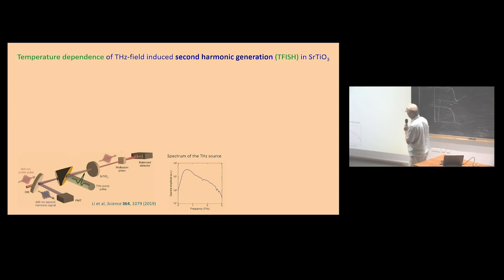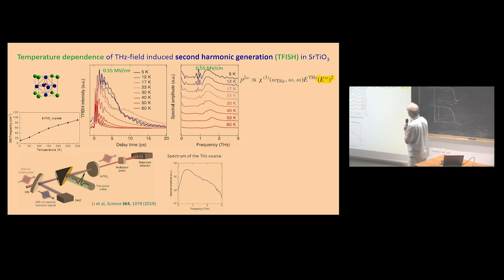In the same issue of Science another paper was published from the group of Nelson, and they again investigated strontium titanate, but they pumped it with a single pulse with the peak around 0.7 terahertz. They pumped the strontium titanate and probed it at 800 nanometers, and they measured second harmonic generation. And again, they observed a strong increase of second harmonic generation intensity. If you calculate the Fourier transform, you see one single peak, which corresponds to double the soft mode phonon frequency, which softens on cooling. And then it splits at low temperatures, probably due to a change of symmetry in this system.